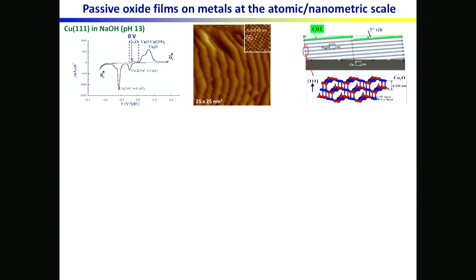Now, we can also look at much higher resolution, and this is here the high resolution image recorded in situ. It's without filtering, and it's in the direct space. We don't use Fourier transform to get this. So this is the direct space image of the structure of the oxide that is forming on the surface. And you can see that it is a hexagonal arrangement. And if we measure the distances, this corresponds to the formation of Cu2O, the 111 plane of Cu2O.